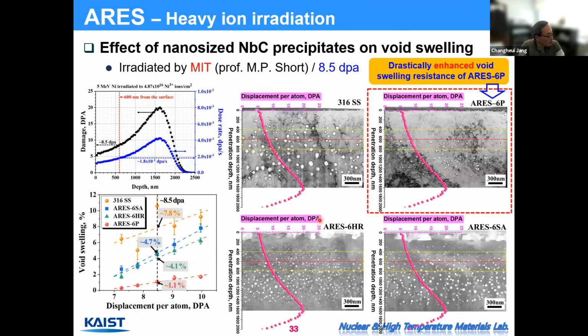So the key issue of void swelling has to be experimentally confirmed by ion irradiation. So we have one ion irradiation at the level of 8.5 dpa at MIT. This one is comparing the conventional 316 stainless steel and our alloys. We can see there is a significant reduction of the void size. And actually the volume change of conventional 316 stainless is around 8%, and we are around 1%. So there is about a 7 times decrease in the swelling.